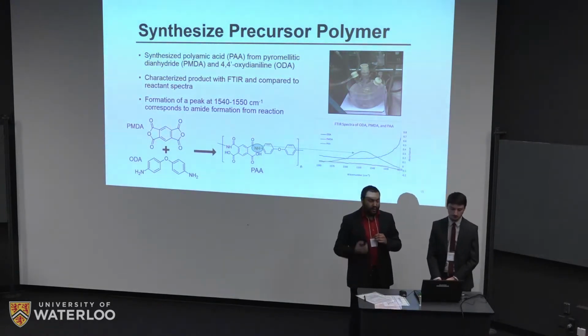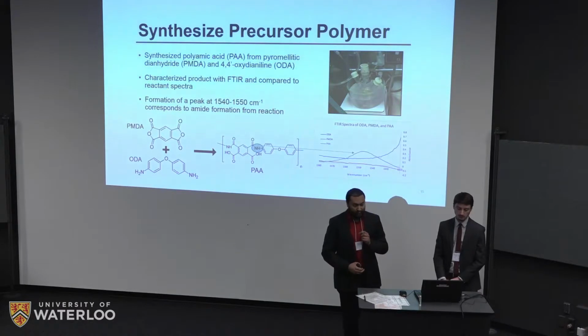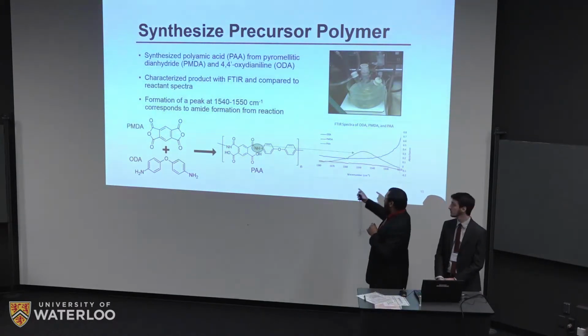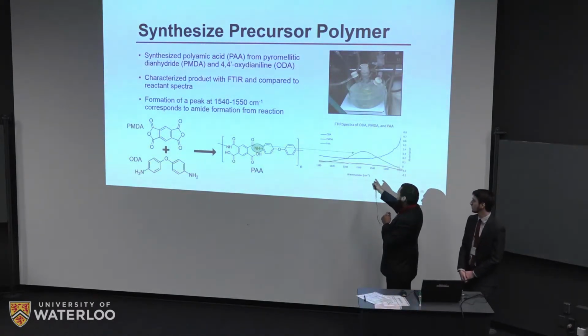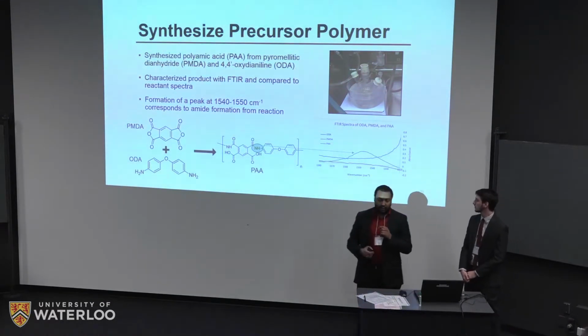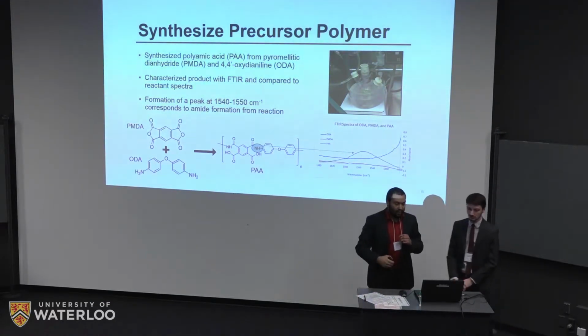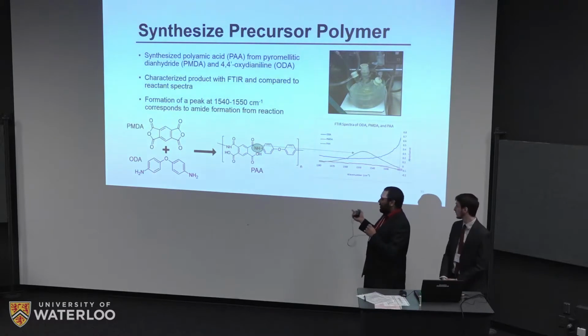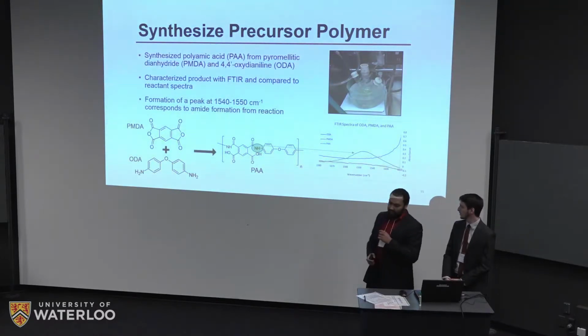And then we characterized it using FTIR. The formation of a peak right here, about 1550 to 1540 wave number, is characteristic of an amide bond. And so we took this as proof that we successfully made the PAA.